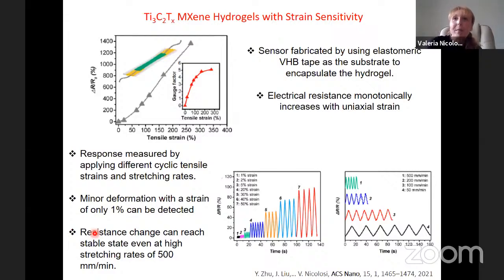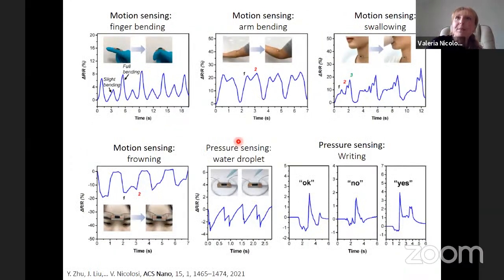Because of the nice conductivity, we managed to use that as a strain sensor as well. Again, you could track the conductivity or the resistivity as a function of the tensile strain. And we use that to make all sorts of motion and pressure sensing. Here is on a finger. You can really see the bending on the finger when it goes on and off. Here is put on an arm that is bent in this way, and you can track the motion. Here is in the throat, and you can track swallowing, for example, the 3 phases of swallowing. Here on the forehead, you can see the expression lines moving.